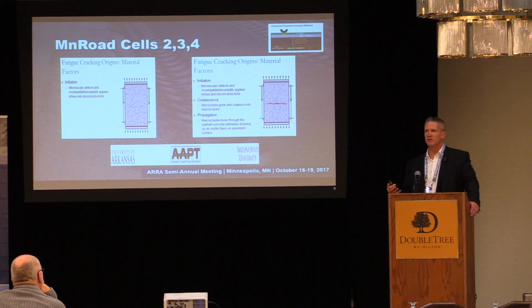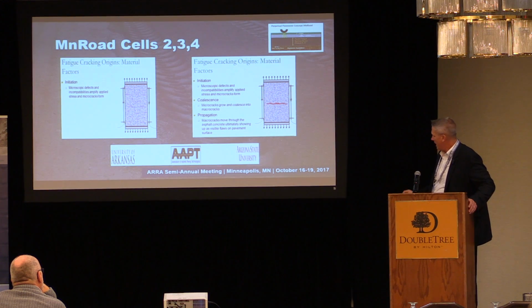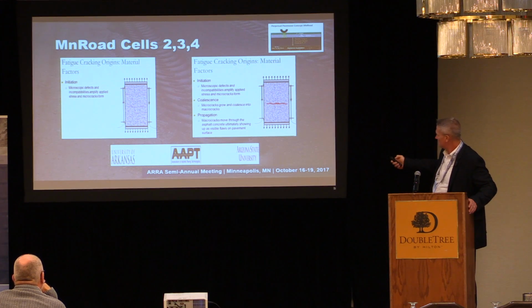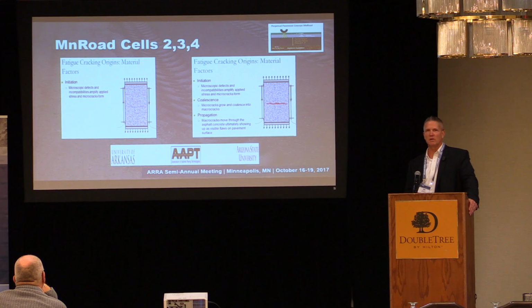It doesn't behave like certainly a cement material or something that's more brittle. But because of the higher void value, because of the softer binders involved, the cracks, when they do form, find a hard time. They don't find a path to get through that material in order to propagate up through that overlay, and that's why those overlays are not seeing cracking for a much longer time than they normally would see when they're placed on top of an unbound base.